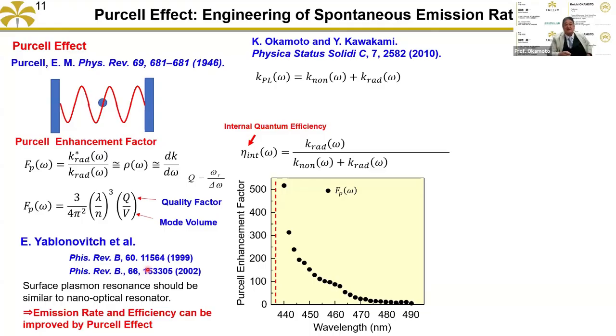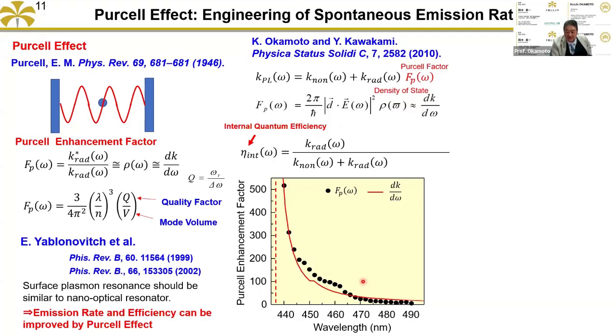Then experimentally we showed that. The spontaneous emission rate is determined by the non-radiative recombination rate and the radiative recombination rate, and the Purcell enhancement factor is proportional to the density of states by Fermi's golden rule. The Purcell enhancement factor is obtained from the experimental time-resolved experiment, and the density of states we can calculate from the dispersion diagram. This value is very close. That's why this result supports our model.